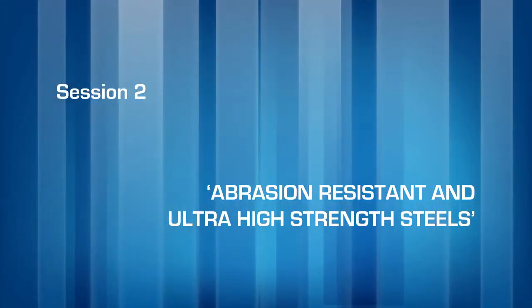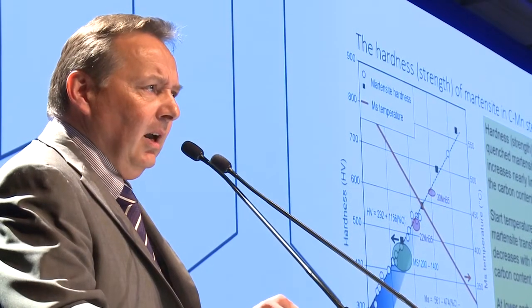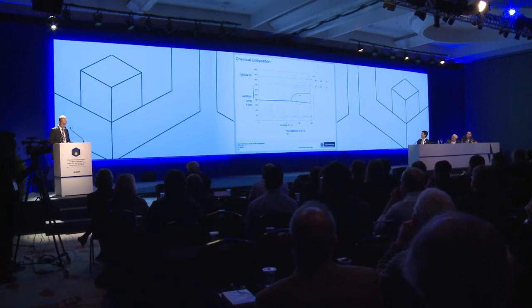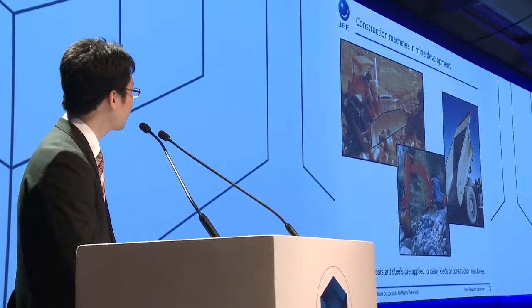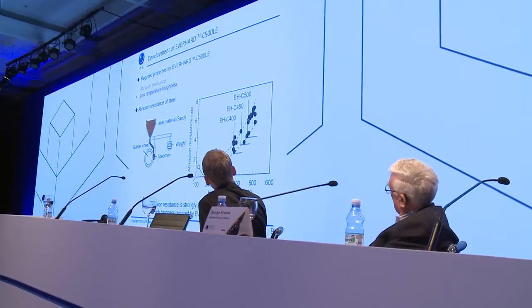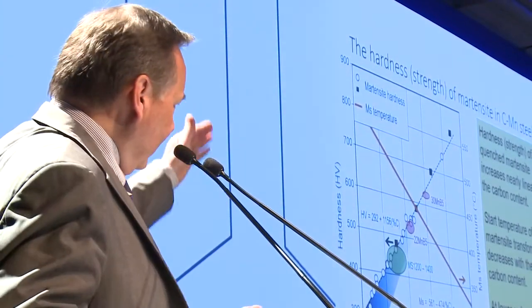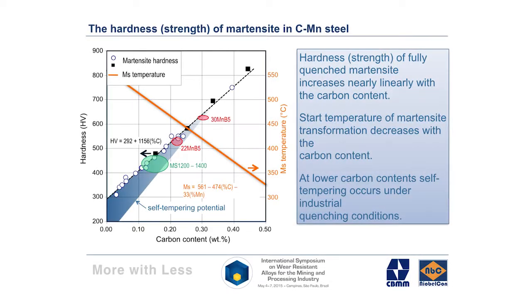Abrasion-resistant and ultra-high-strength steels. In this session, most papers concentrated on specific developments of steels for particular applications. International contributions from steelmakers, equipment manufacturers, and universities combined to provide further insights into the way in which hardness and toughness can be combined to produce optimum wear resistance in plate and tool steels, particularly with martensitic products. It was revealed how in quenched steels, martensitic hardness is largely dictated by carbon content, and the martensite start temperature by carbon and manganese levels.